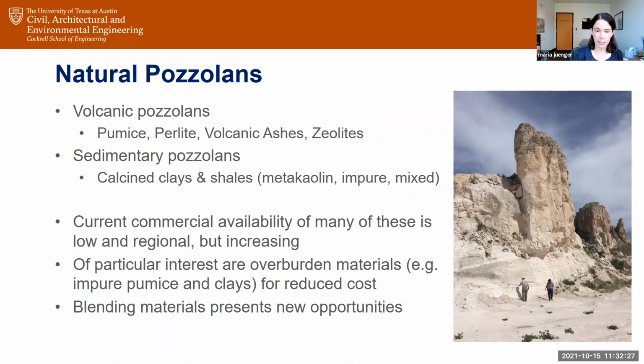One of the really good candidates for supplementary cementitious materials are natural pozzolans. These are volcanic materials like pumice and perlite, volcanic ashes, and zeolites, similar in many ways to what the Romans used in their concrete mixtures. And then sedimentary pozzolans, so calcined clays and shales that don't simply have to be quarried, but need to be heated, or calcined, at a high temperature. Whereas fly ash is decreasing in availability, the current commercial availability of these natural pozzolans is actually increasing. But because you need, in many cases, a volcano nearby geographically to have deposited the volcanic minerals, they can be really limited geographically, but not in all cases.